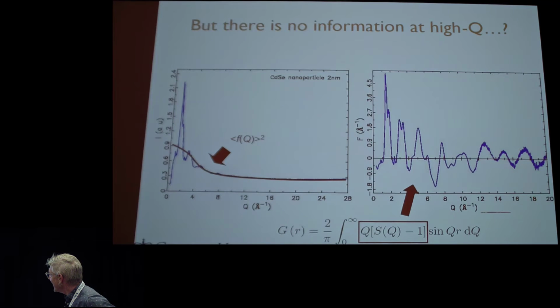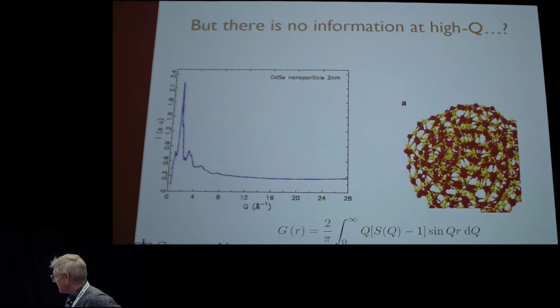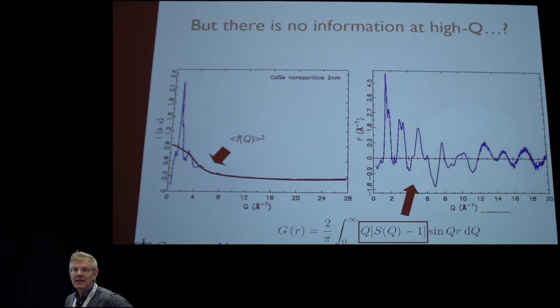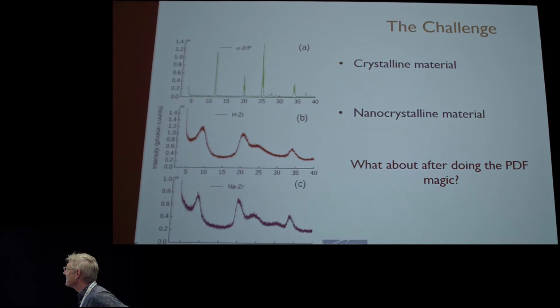So this is high-Q. And if we go back and we look at high-Q, it looked like the data were flat and there was no information in the data. But after we do the normalization, we see that there is information in the data. And if we measure with enough statistics, with good enough signal to noise, we can extract that information and we can use it for our structure determination.